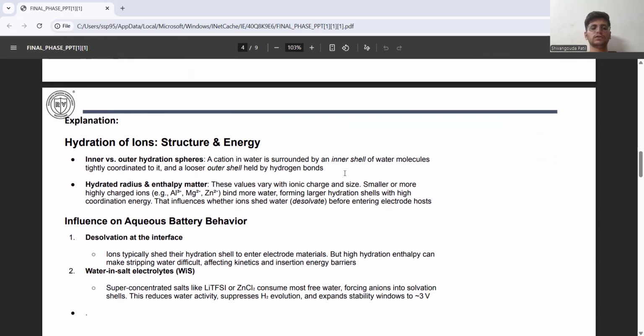Hydration of ions: structure and energy. Inner versus outer hydration spheres. A cation in water is surrounded by an inner shell of water molecules tightly coordinated to it and a looser outer shell held by hydrogen bonds. Hydrated radius and enthalpy matter. These values vary with ionic charge and size. Smaller or more highly charged ions bind more water, forming larger hydration shells with coordination energy that influences whether ions shed water, or desolvate, before entering electrode hosts.